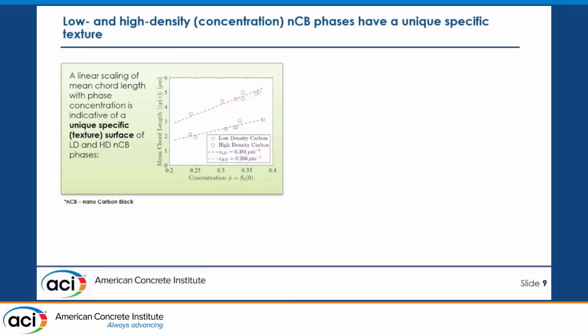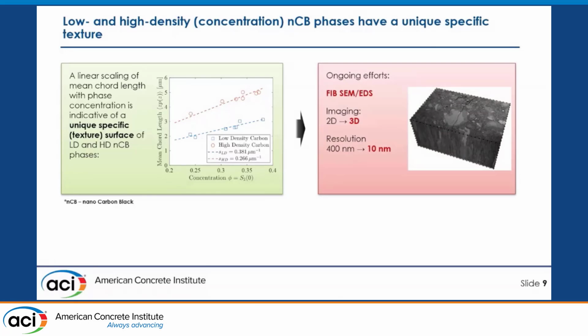For analysis of these two phases, low density and high density concentration phases, we employed statistical descriptors, namely the two-point probability correlation function. We obtained mean chord length, which can be seen to scale linearly with the concentration of nanocarbon particles. So this is indicative of the unique specific texture of these phases, and at the same time shows us that no matter what type of nanocarbon black we use, the process is highly repetitive and reproducible at different configurations. Currently, we are also investigating it in 3D using FIB-SEM techniques to reduce the resolution further.